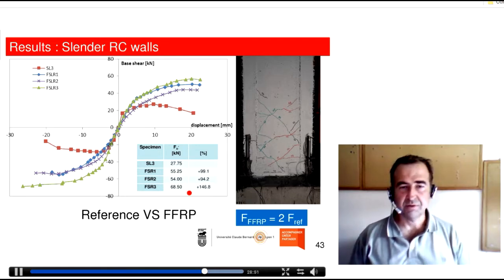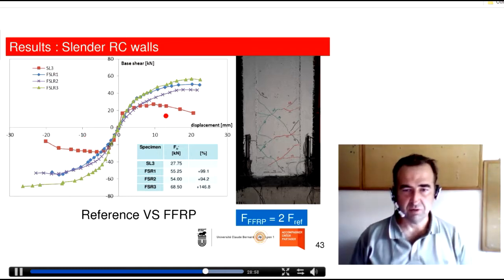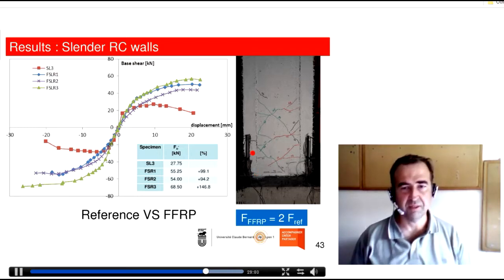If we compare the results, this is the reference specimen, you can observe a very brittle failure, mainly due to longitudinal cracks in flexure appearing in the basement of the wall. And when the wall is strengthened with FRP, flax, you can observe a very important increase in the horizontal load capacity. And this increase, compared with the flax fibers, is very nice. And we'll see that it is also interesting for dissipation capacity.